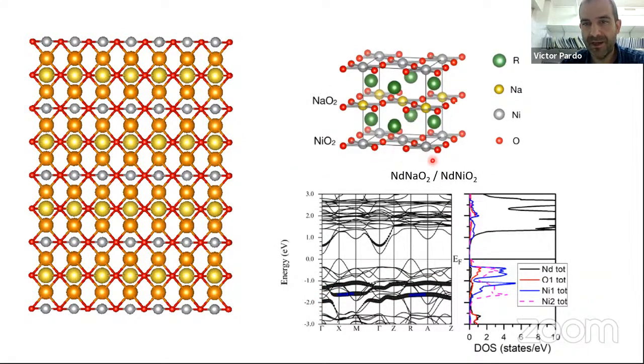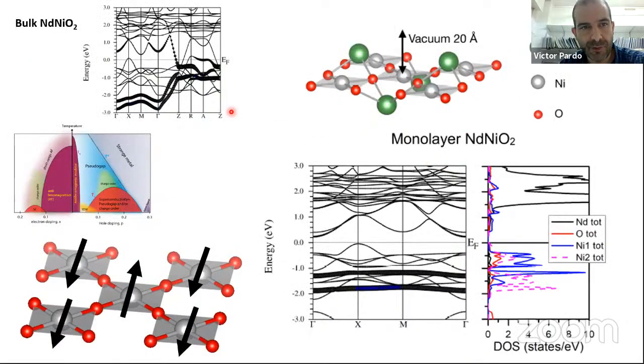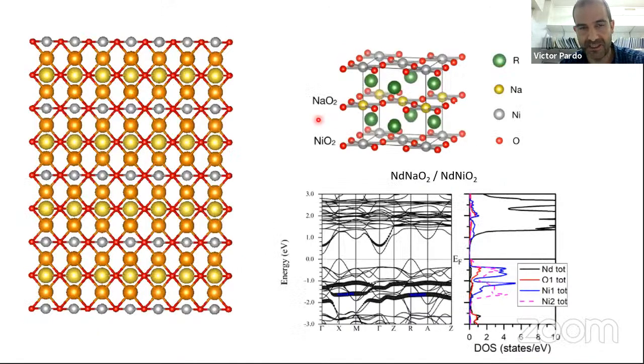It's an insulator. It's an antiferromagnetic insulator in the plane, and the d z-squared bands are basically non-dispersive. So what is happening in the bulk neodymium nickel O2, you remember these hugely dispersive bands, they occur thanks to the nickel-nickel off-plane hopping along the c-axis. Well, okay, this is just a toy model. So, are there any other systems where this can be happening?